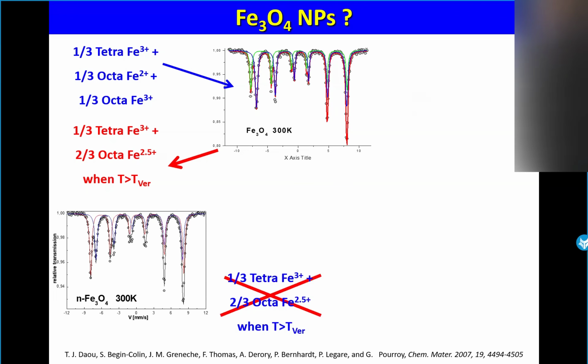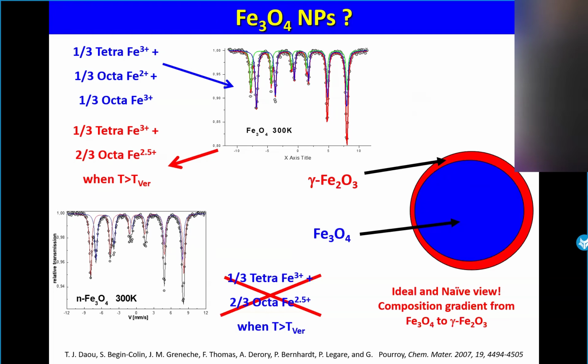So now, if you have some nanoparticles of, let's say, magnetite, what you can see is that you also have two components. But if you look carefully, the outer component is larger than the inner component. So if you look carefully now, the mean value of the isomer shift is decreasing. That means there is a tendency from iron 2 plus and iron 2.5 plus to iron 3 plus. That means there is some oxidation. And of course, the surface might be oxidized, so you will have a transformation of Fe3O4 into gamma Fe2O3, maghemite.